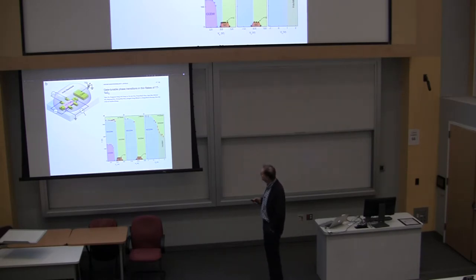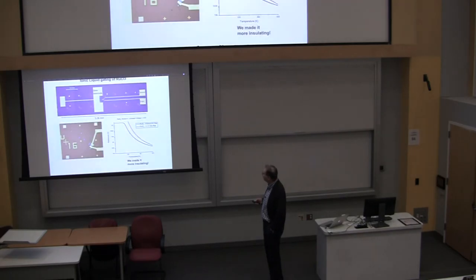So that's interesting. They're able to get a whole phase diagram here: nearly commensurate charge density wave, incommensurate charge density wave. So it turns out we tried some ionic liquid gating with ruthenium trichloride. We were trying to metallize it, and we failed. We ended up making it more insulating. So it didn't work for ruthenium trichloride. That was why we were so excited that we were able to get it, even though it just made it more magnetic. It didn't make it a superconductor, it made it more magnetic.